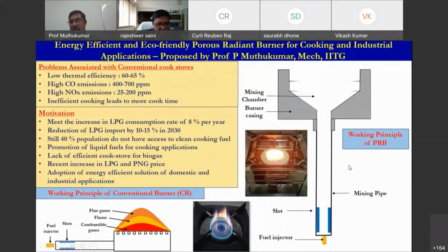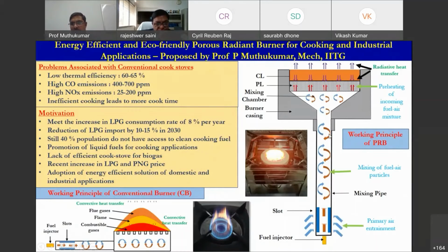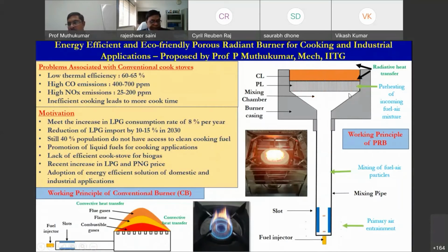And coming to our technology, basically it's a porous radiant burner, which consists of two layers of porous matrix. One is the preheating zone, and the top one is the combustion zone. The preheating zone is made up of low cost ceramic, with low thermal conductivity and low porosity. And the combustion zone, the top one, the brown color that you can see, is made up of high thermal conductivity, high porosity, high emissivity silicon carbide matrix.